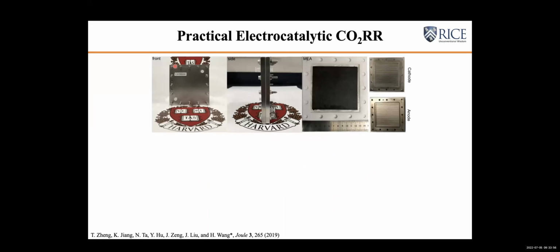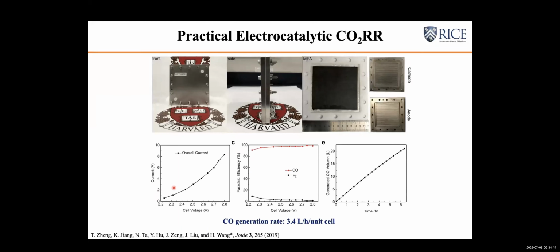Now we can do some of the initial tasks of scaling up by fabricating this 10 by 10, which is about 100 square centimeter electrolyzer, spray coated with the catalyst using our MEA design. Now out of this one unit cell, we can generate 8 to 10 amp of current. So now the current is in a completely different unit. This is amp right now. And out of this one unit cell, we generate about 3 to 4 liters per hour of CO production rate.